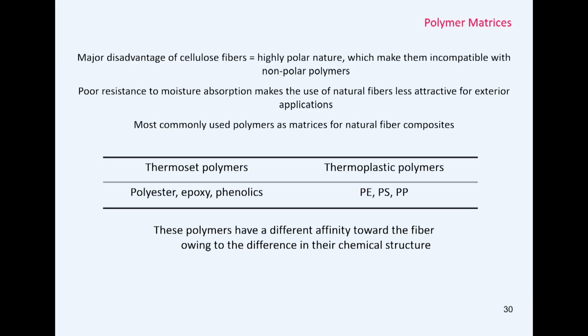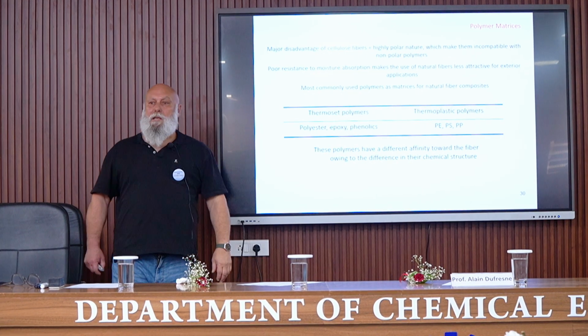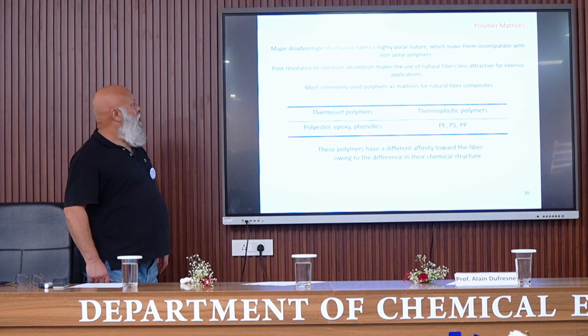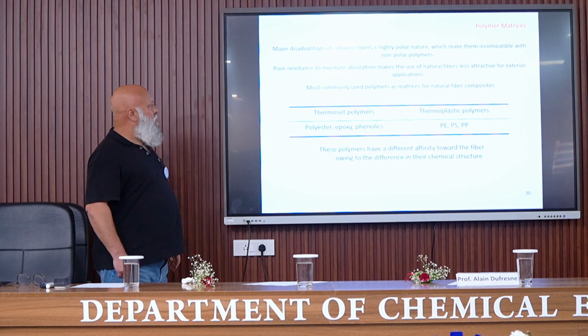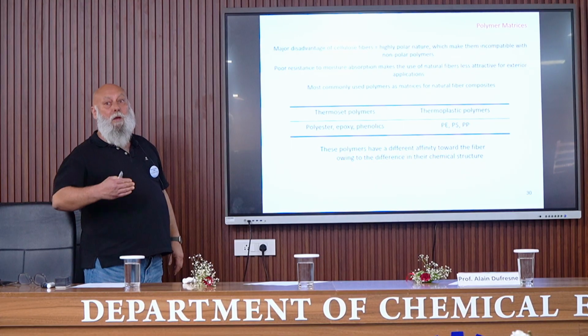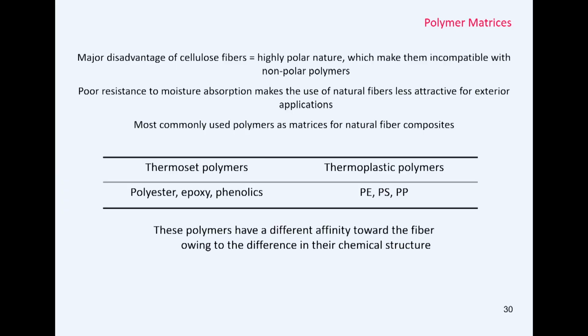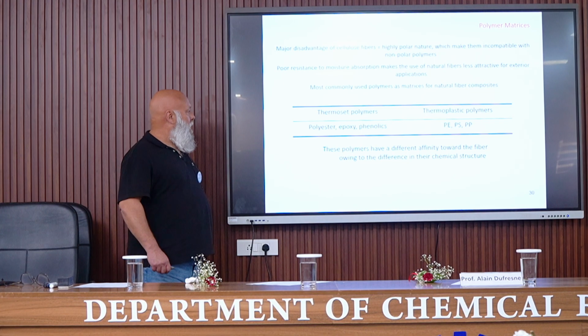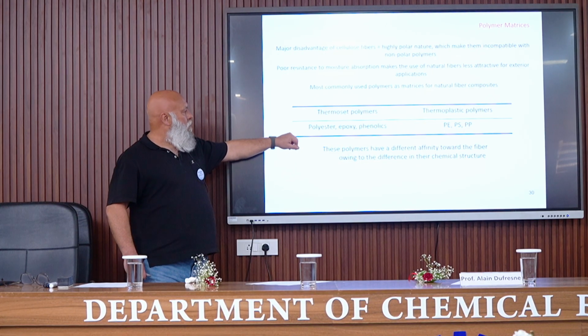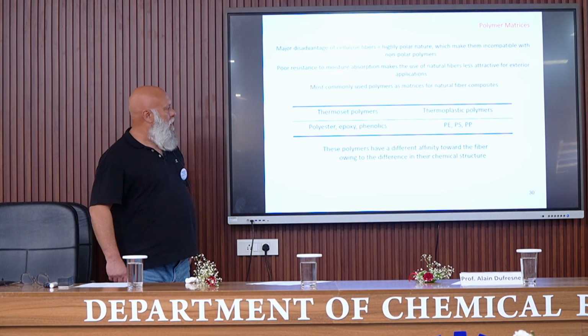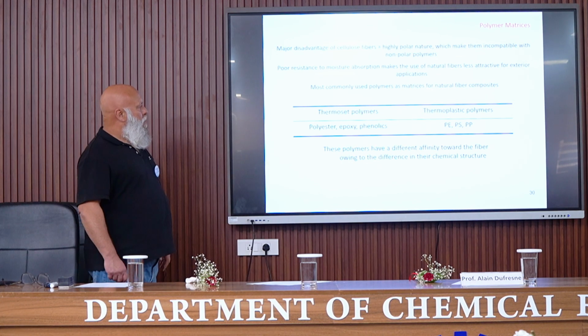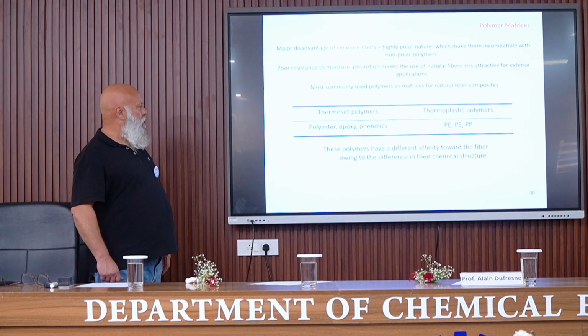So I mentioned previously that one drawback of natural fiber or cellulosic fibers is their polar nature. They are highly hydrophilic. It results in a poor resistance to moisture and difficult miscibility with polymer matrix, which are usually non-polar. So these are the typical polymers that are used in association with natural fibers to prepare composites, or biocomposite. So for thermoset polymer, polyester, epoxy, or phenolic resin, and in the case of thermoplastic polymers, so classical thermoplastic like polyethylene, polystyrene, and polypropylene.